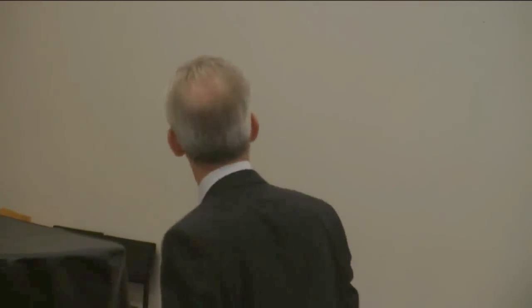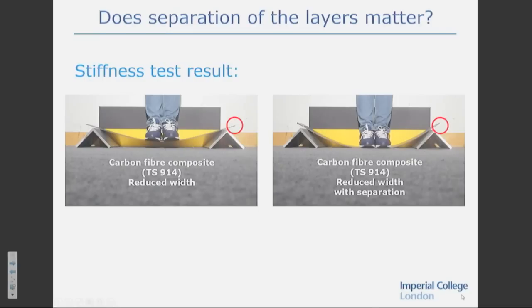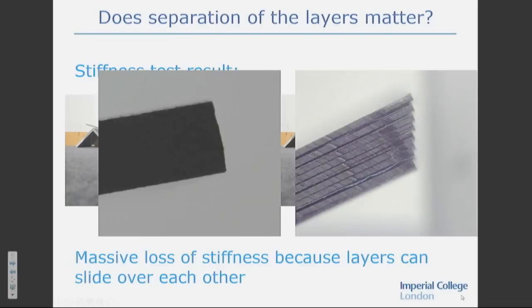So we've lost a huge amount of stiffness. And if we look at the ends of each of these plates, first of all, the intact one, well, there it is. There's the intact one. I'm just showing the profile of the end of the beam. It looks a little bit uneven, but it's to do with how it was cut exactly. But let's look at the other one, the one where the separations are. You can see every ply has slid relative to its adjacent neighbour. And it's because the layers can slide over each other, of course, that we have such a massive loss in stiffness there. So separation matters.